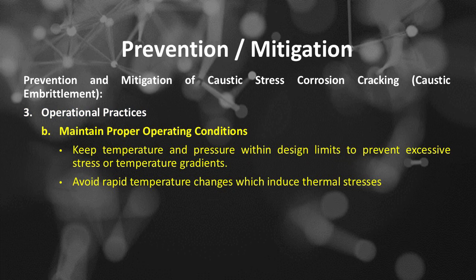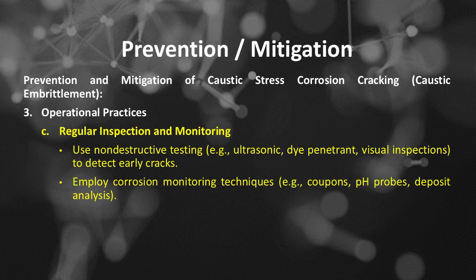Operational practices. Number B is maintain proper operating conditions. Keep temperature and pressure within design limits to prevent excessive stress or temperature gradients. Avoid rapid temperature changes which induce thermal stresses. Operational practices. Number C is regular inspection and monitoring. Use non-destructive testing, such as ultrasonic, dye-penetrant, visual inspections, to detect early cracks. Employ corrosion monitoring techniques, such as coupons, pH probes, deposit analysis.